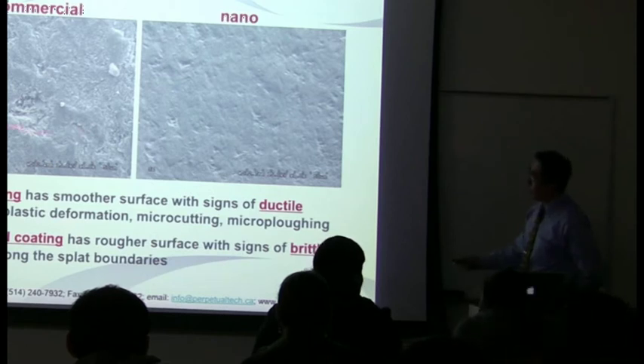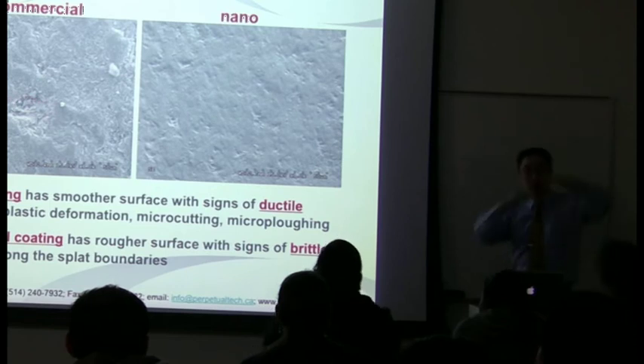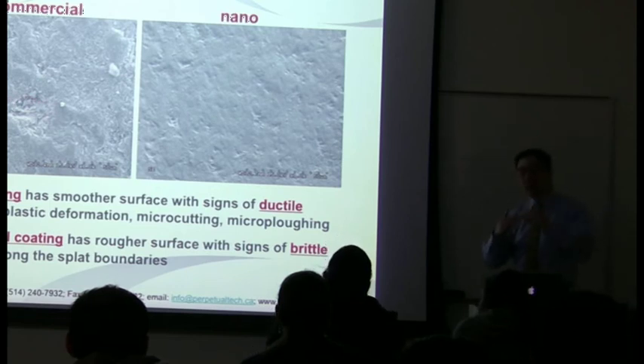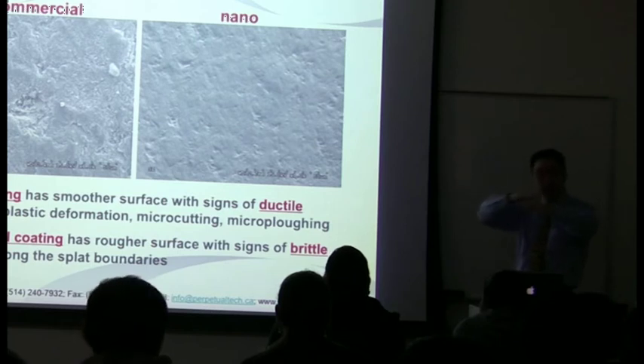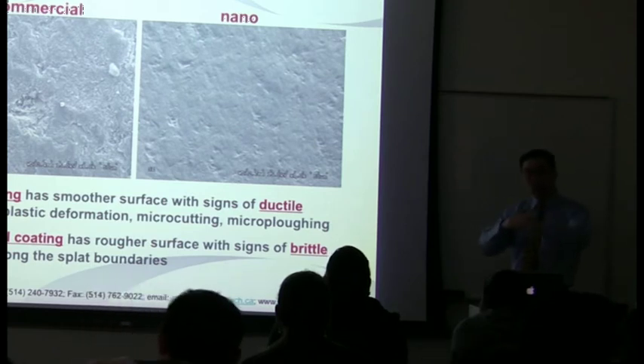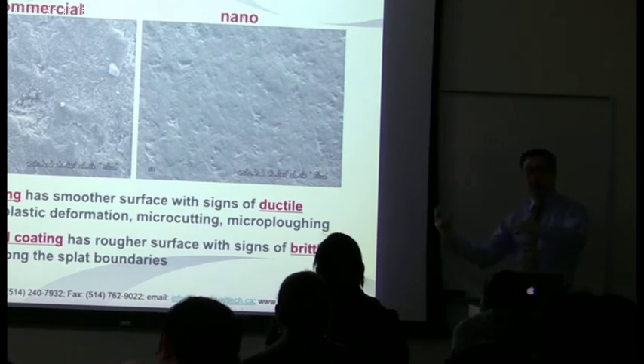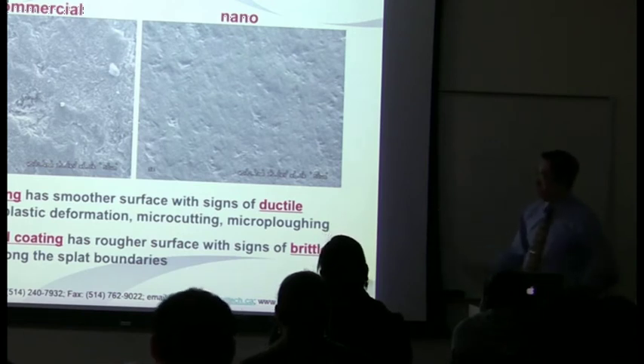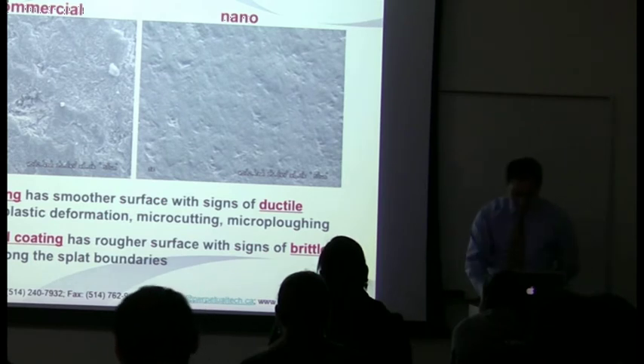What we're noticing here is that the majority of fracture occurs at the splat boundaries, which means one droplet solidifies, the next one comes. The boundary between the two is the weak spot. So it forms a crack there, and that chunk falls off, leaves you a fairly rough surface.